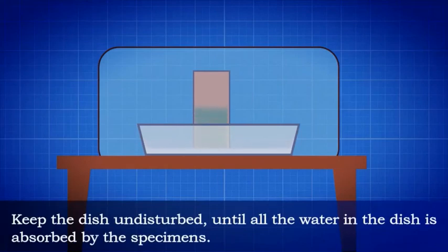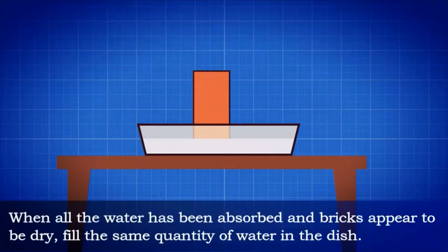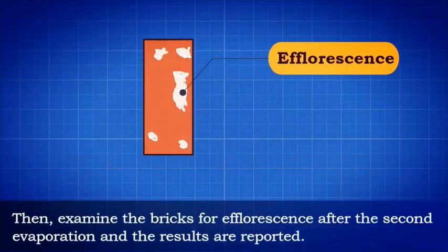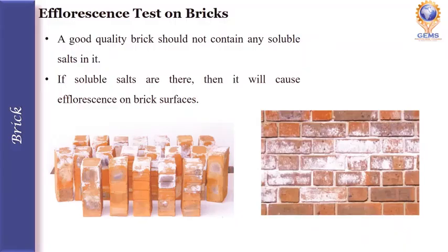Keep the dish undisturbed until all the water in the dish is absorbed by the specimens. When all the water has been absorbed and bricks appear to be dry, fill the same quantity of water in the dish. Allow it to evaporate as before. Then, examine the bricks for efflorescence after the second evaporation and the results are reported.